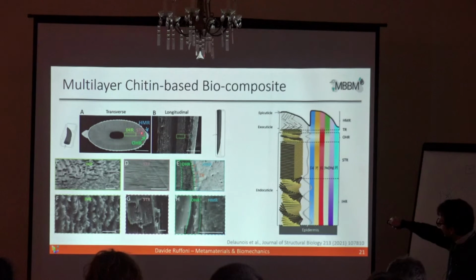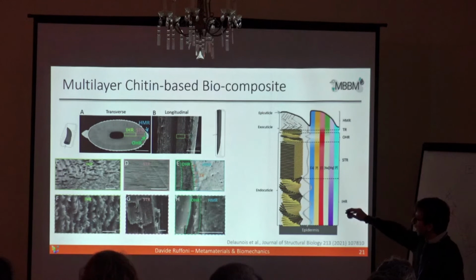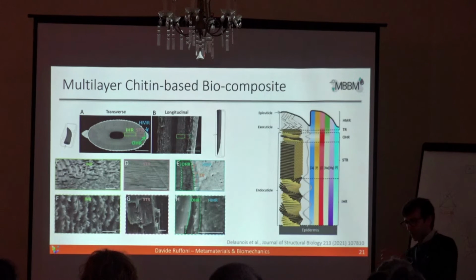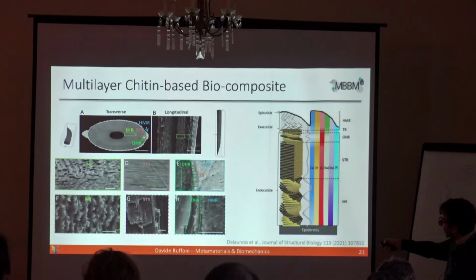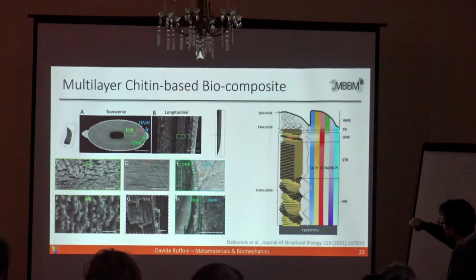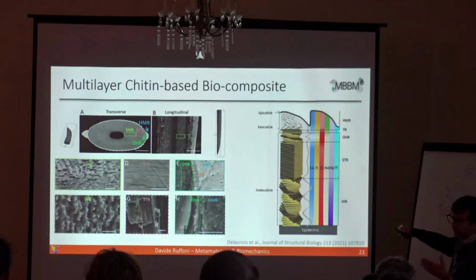And then in the middle layer, what we call the striated region, we see that fibers are all parallel with each other, and in this picture here they will come out of the screen. So this is already a strategy to reinforce the spike longitudinally, because we see a lot of fibers running longitudinally. And what surprised us quite a lot is that there is a small layer here, you can see a bit, which is composed once again of a Bouligand structure, a much thinner Bouligand structure, and then there is the outer layer which is highly mineralized. It's white here, so this means high mineral content, which has no fibers.